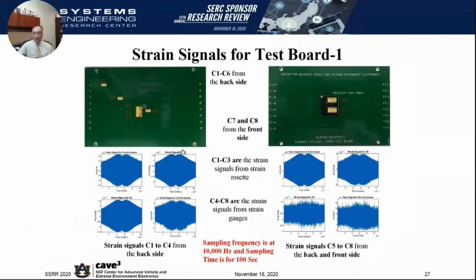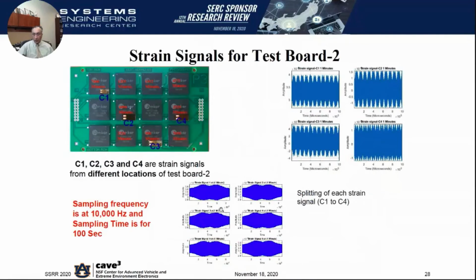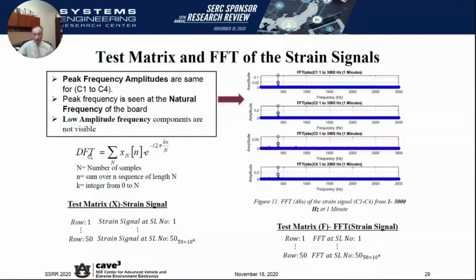So for most part, we have relied on spectral domain analysis. So we take time domain data from the various sensors, and I've already highlighted where the sensor locations are. So that's what the time domain data looks like. That's for board 1, that's for board 2, time domain data. And you can actually see what the time domain amplitude looks like. There we have a peak closer to the natural frequency as the frequency sweep is going on in that narrow window. We take that information into frequency domain, and the tool that we have used is the discrete Fourier transform. There are 50 data sets throughout the lifetime of the board assembly that we progress through failure till after failure. And so these are the various sensor locations.